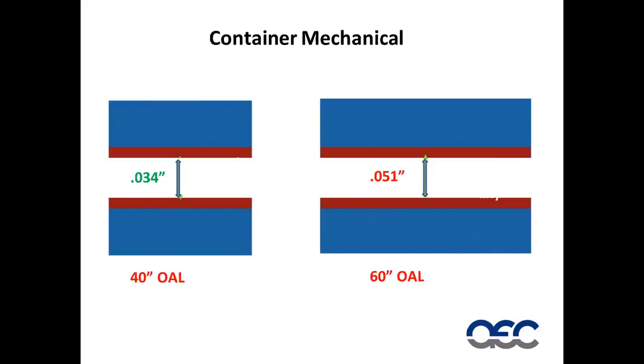There's also some mechanical features to the containers. And today we're seeing containers up to about 60 inches in length. The challenges with longer containers: if we take an 8-inch container that's 40 inches long and a standard 2-piece container, we get about 34 thou expansion under pressure in the center of the liner. If we take that same geometry, same container, and make it 60 inches long, the ID of the liner will expand 51 thousandths of an inch. The problem is, and we've said it prior, that if the gap between the dummy block and the liner becomes greater than 20 thousandths of an inch, we will extrude by the dummy block. So in these longer containers, we need to do something.